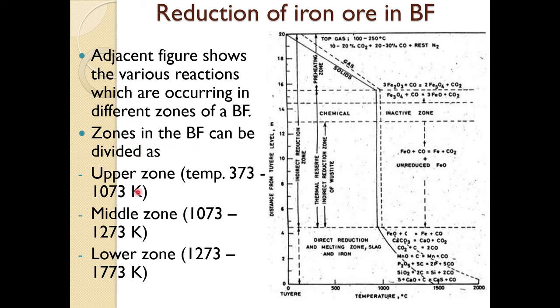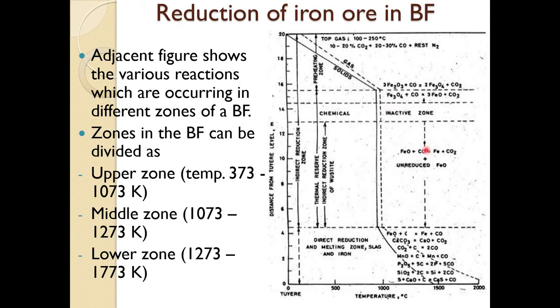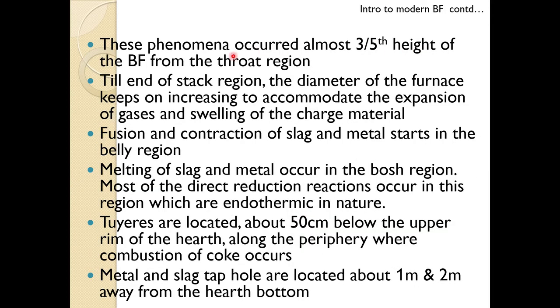The zones in the blast furnace can be divided into upper zone, middle zone, and lower zone, where direct reduction by carbon takes place. The phenomena described — indirect reduction and decomposition of carbonates except calcium carbonate — occur in approximately the upper three-fifths of the furnace height from the throat region. The furnace diameter keeps increasing through the stack region to accommodate expansion of gases and swelling of charge material.